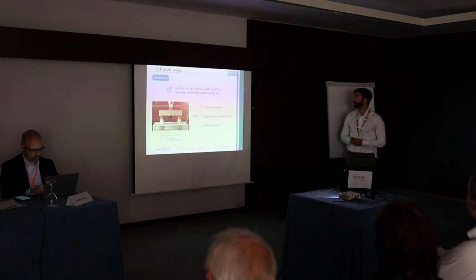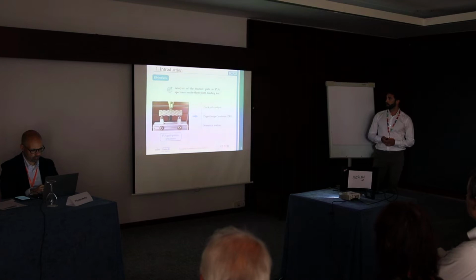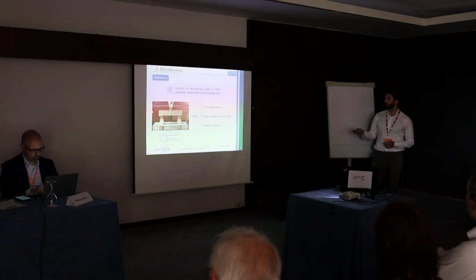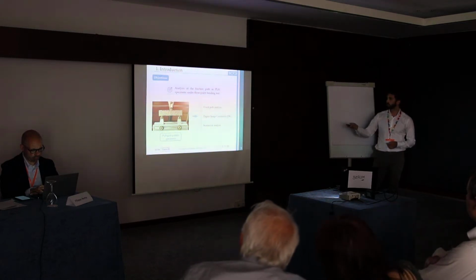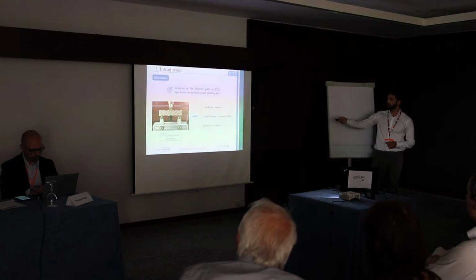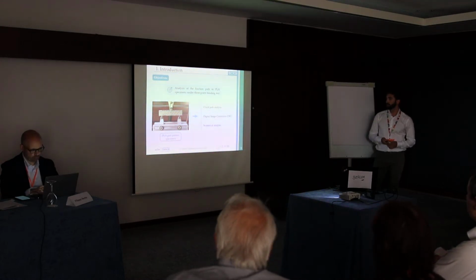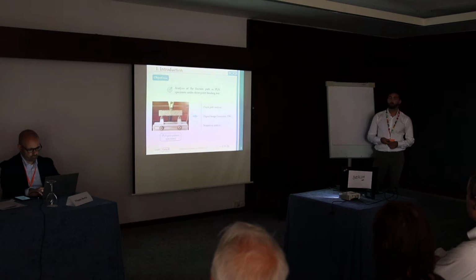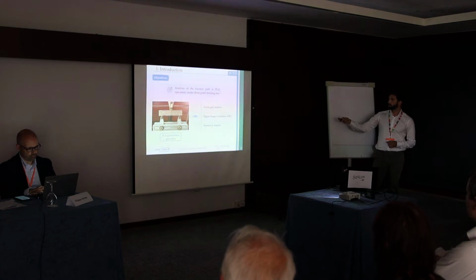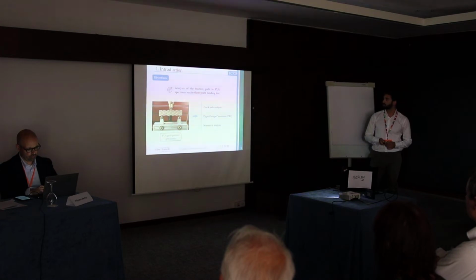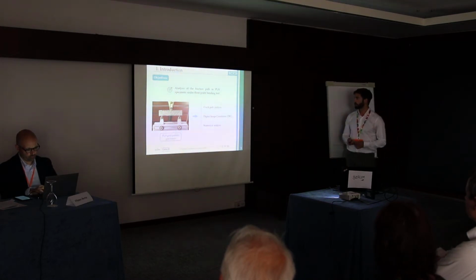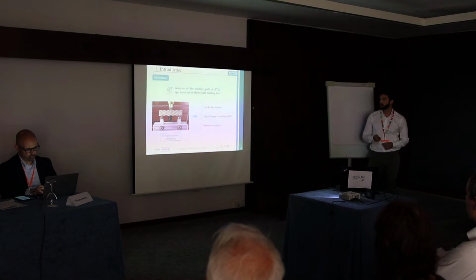Okay, so the aim of this study is the analysis of the fracture path in PLA specimens under 3-point bending. We will focus just on no-shell specimens, just with an infill and a grid pattern infill, and this will allow us to study this widely common lattice architecture in this kind of specimens. For that, we are going to implement the digital image correlation technique to study the strain field in all these tests, and numerical analysis, as I mentioned before, with a phase field prediction.